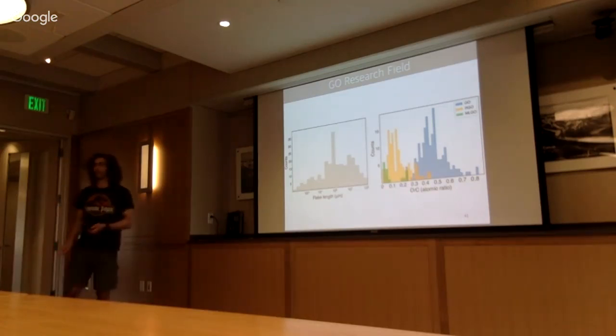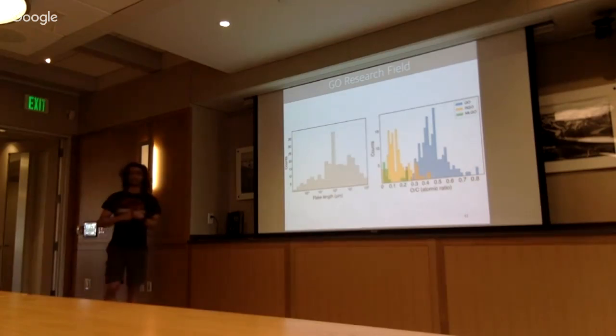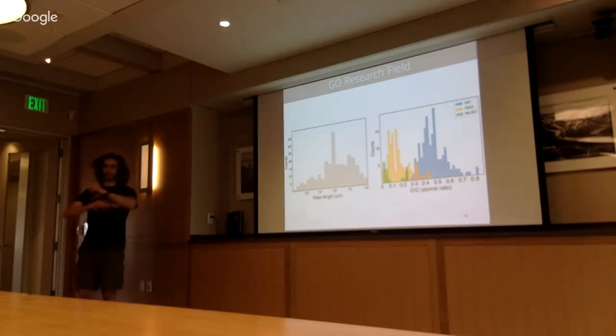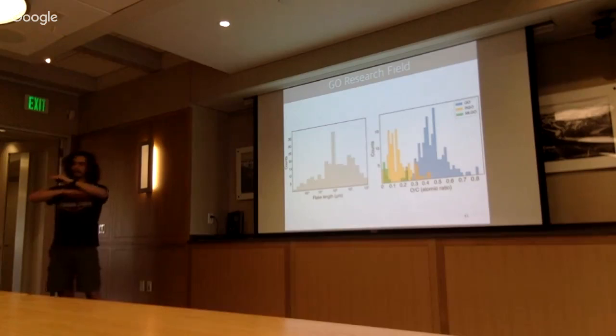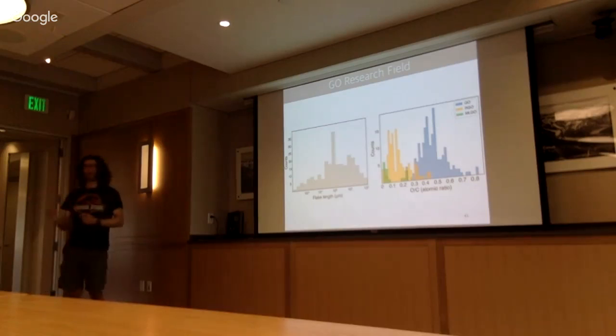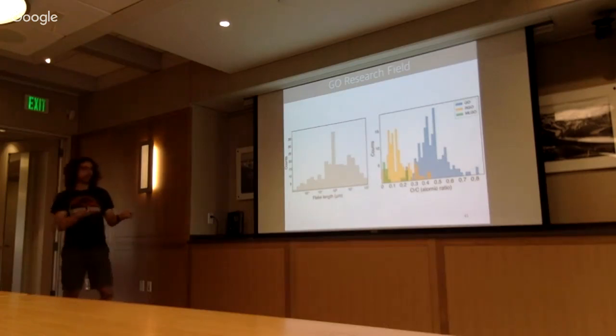And then you have, in green, multi-layer graphene oxide. Multi-layer graphene oxide is when instead of having just a monatomic sheet, you have multiple layers, but you cannot have oxygen functionalization in between the layers. So this is why you have a lower oxygen content.